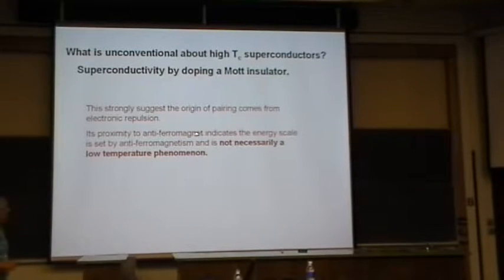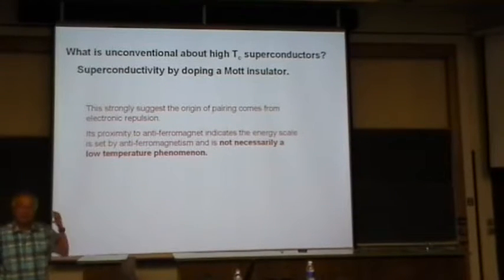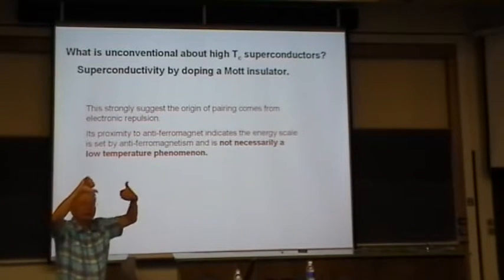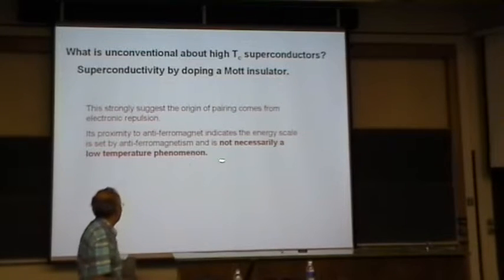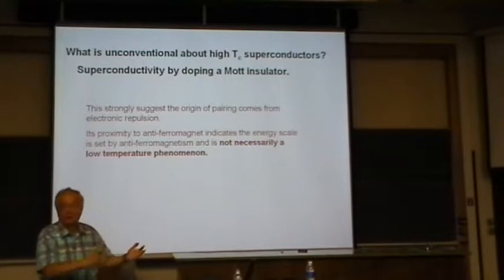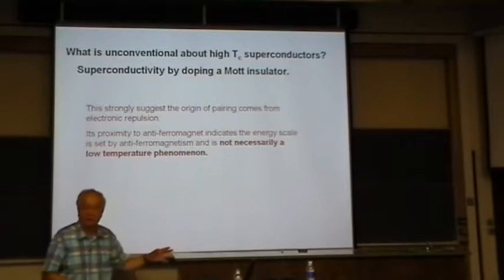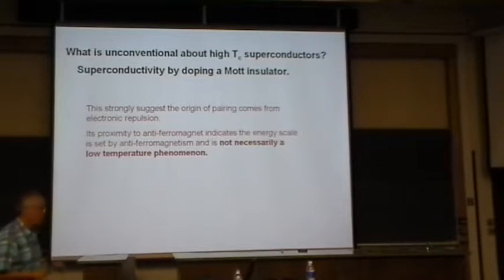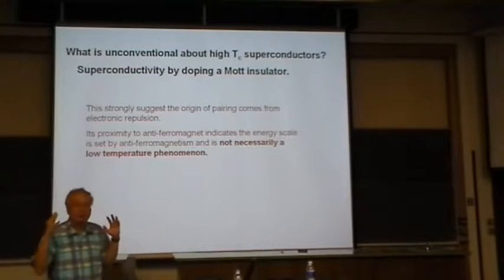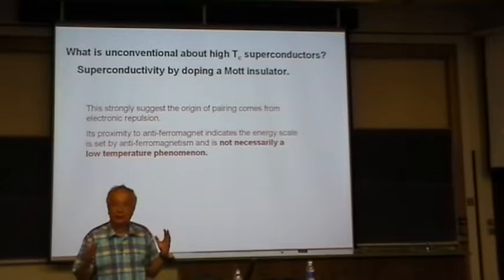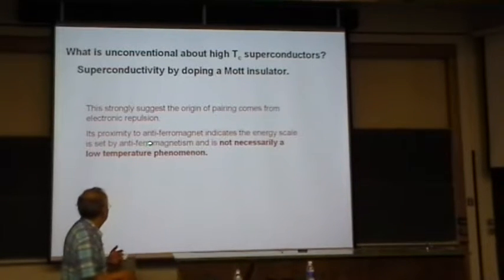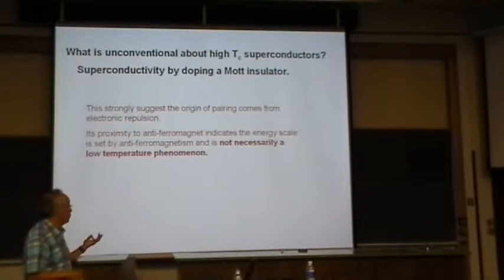And the proximity to this antiferromagnet indicates that the energy scale should be set by this antiferromagnetic scale, what causes the spins to be antiferromagnetic, rather than this lattice vibration scale, this phonon scale. Okay? And so that's a big revelation because it frees us from this very low temperature energy scale for superconductors, because this antiferromagnetic scale is not necessarily a low temperature phenomenon.